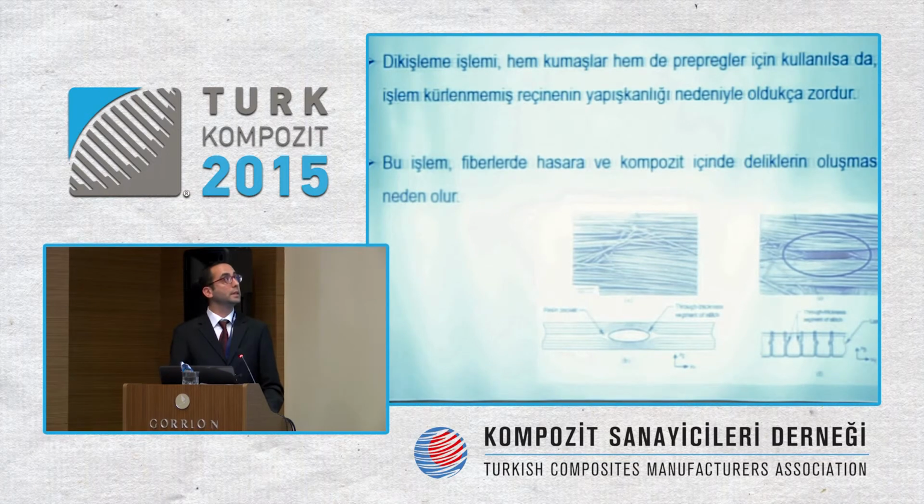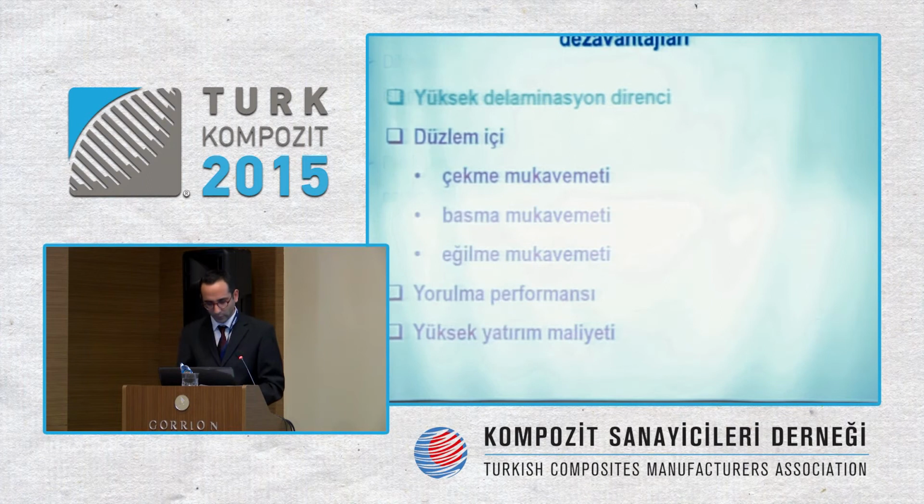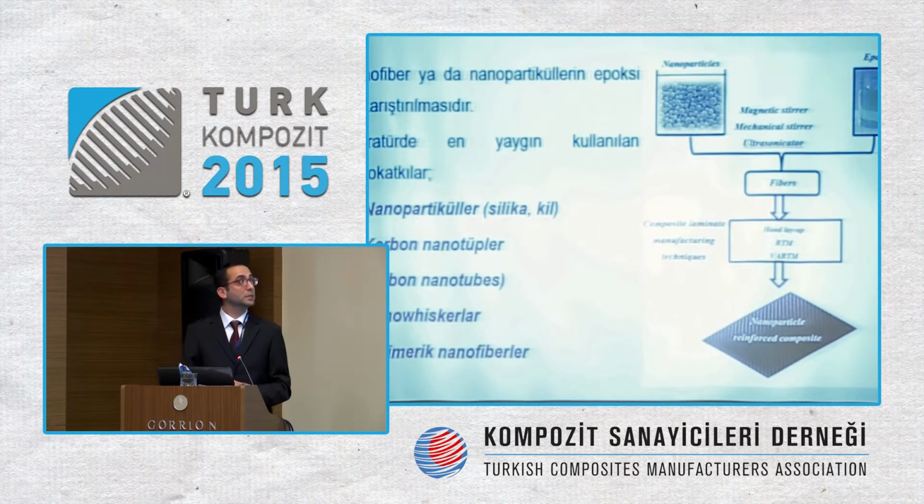And stitching is done over industrial sewing machines with high resistant yarns, and the adhesiveness of the resins may give difficulty to the needle of the machine, and such double way direction may damage the fiber, and we may see certain holes in the fiber. Those two methodologies increase delamination resistance, but in-plane waviness also may appear, the compressive strength and tensile strength will decrease, the fatigue performance also goes weaker, and the cost of those machines is high.